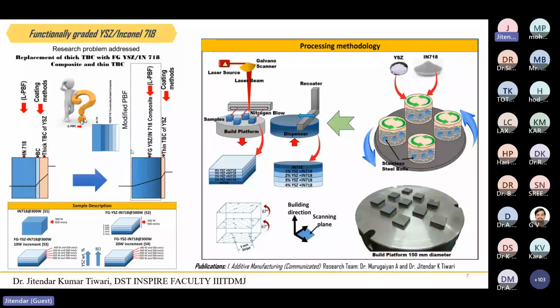But the problem statement here is when we use any kind of high temperature material, let's say Inconel 718, we need a bond coat. There is a TGO also there, thermally grown oxide, and this bond coat is there. The purpose of this bond coat is to avoid the thermal mismatch between the Inconel 718 and this thermal barrier coating, YSZ, yttria-stabilized zirconia. So what we can do, we can replace this whole system with the functionally graded YSZ in Inconel 718, because in that case the thermal mismatch will be lowest.